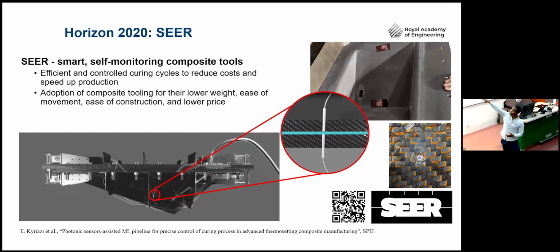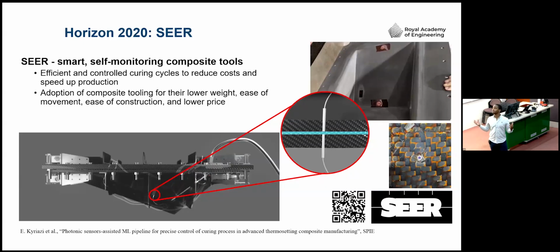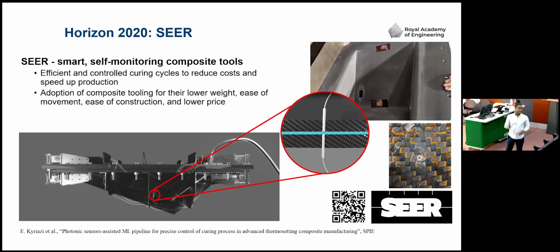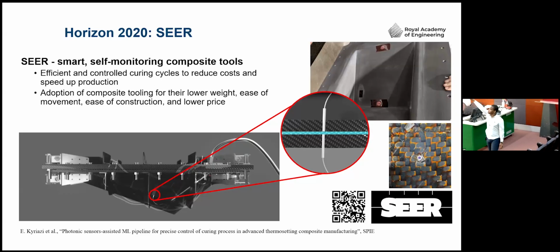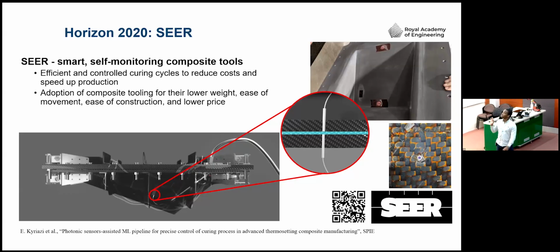So on paper, this self-contained composite tool, which was used to make other composites, is able to self-monitor and make changes based on what it thinks it needs, based on a set of machine learning algorithms. The key challenge from our side at Cranfield was that these sensors are about 2 millimeters in diameter. How do you get them into the tooling? They have to be absolutely flush on the surface, perfectly straight within, I think, a 5-degree tilt angle. And flush on the surface meant something like 5 or 6 microns, because it needs to touch the resin on the inside, otherwise you don't see anything.